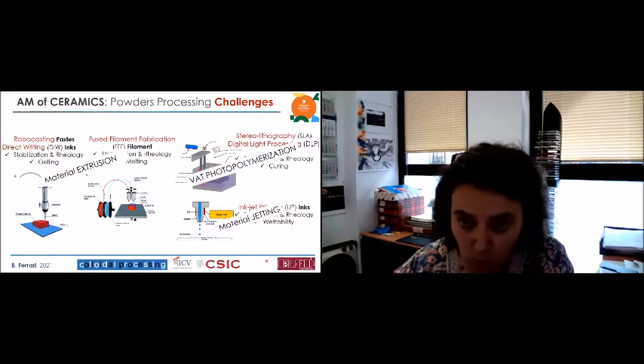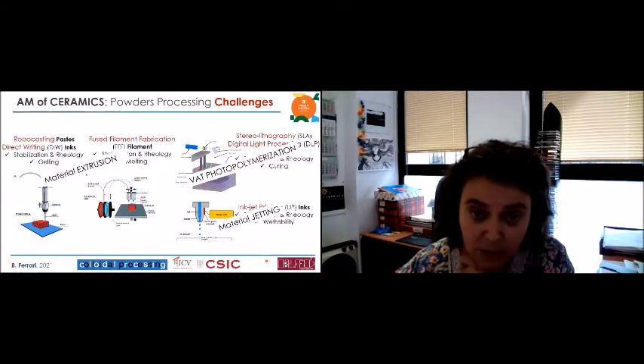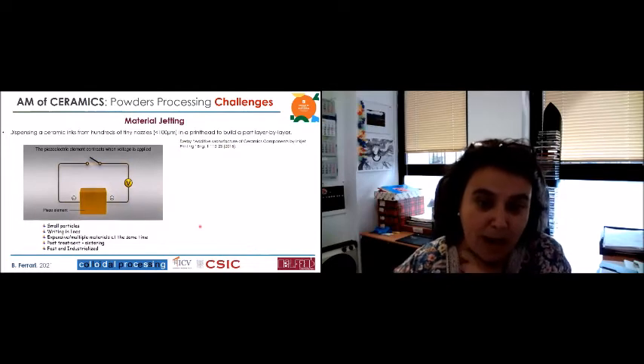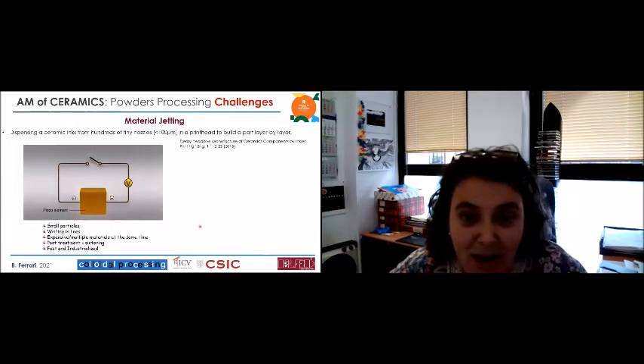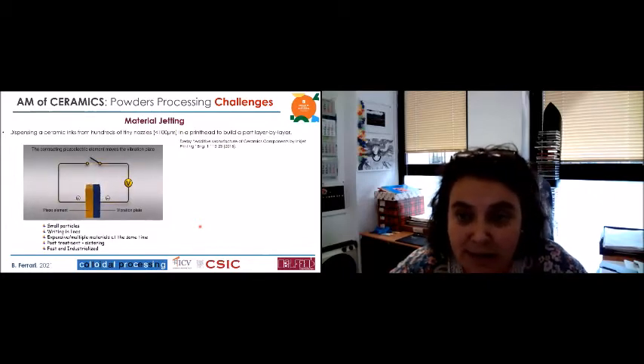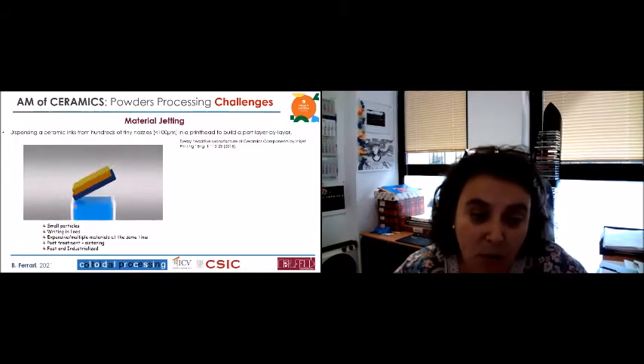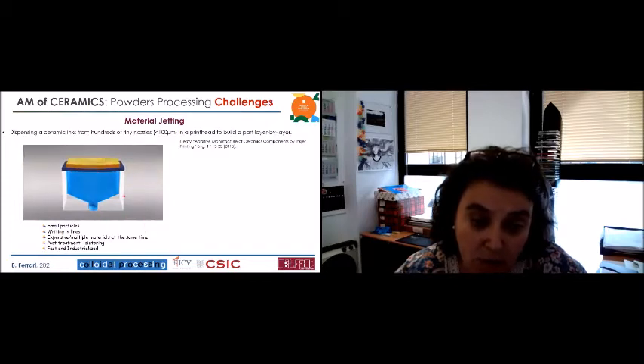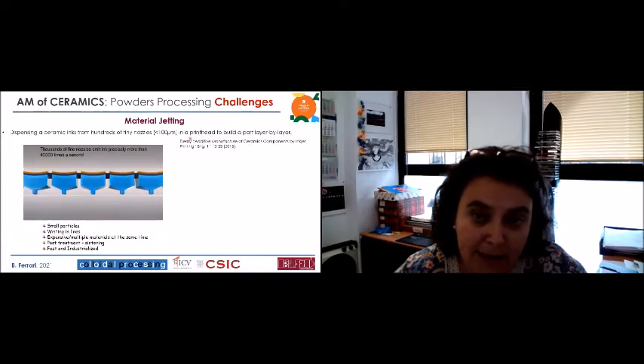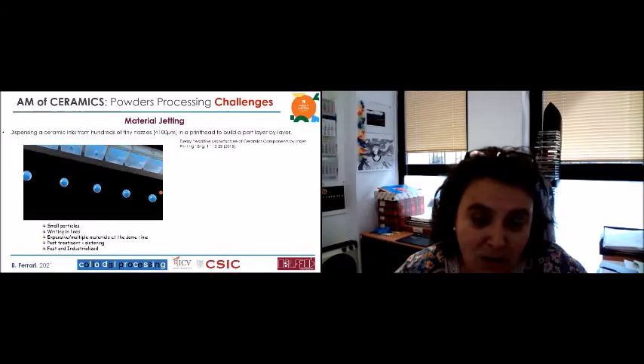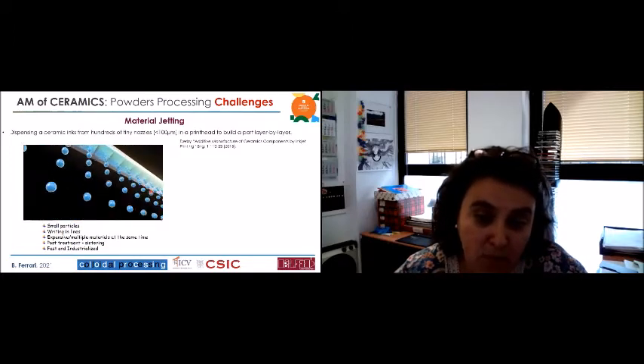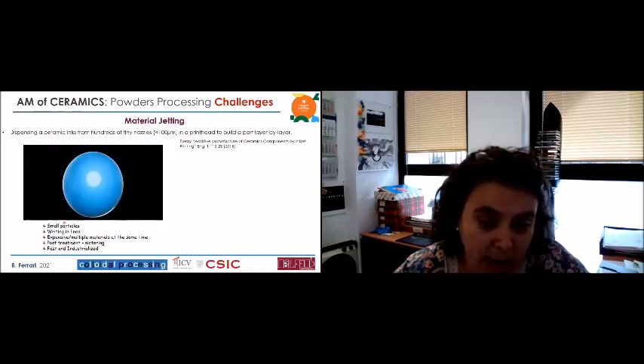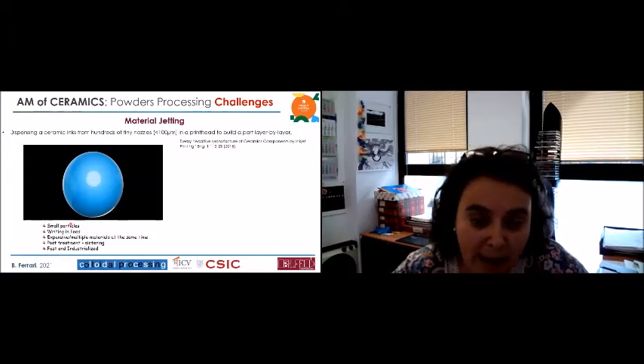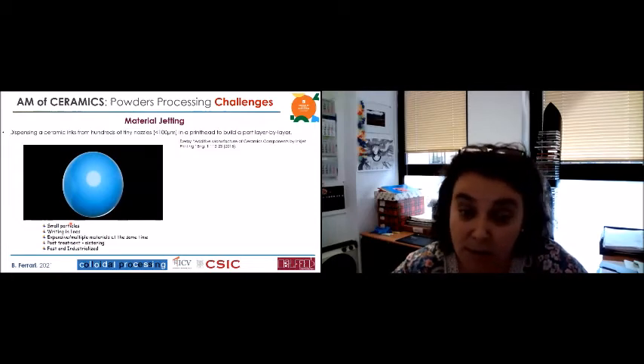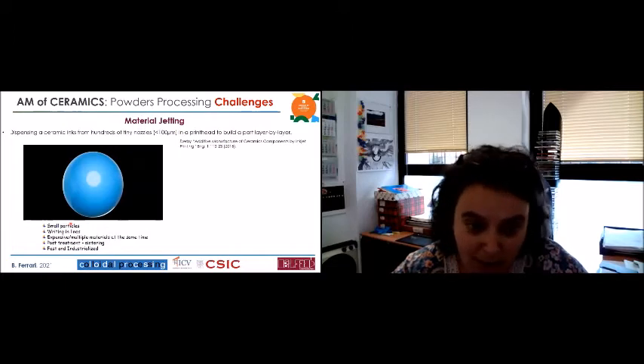So there are three groups of processes in ceramics that should be described a little more in detail. Here you have the material jetting technology, right. This is inkjet printing. And here you can see that we use a piezo element to promote the formation of some drops, right, in a head that has many of these nozzles that you can see here, and you are promoting the formation of a design, right, a pattern. You are using here very small particles. You are writing in lines here. This is really expensive equipment that we are using here, but we can use many materials in the same head, right? And we need a post-treatment.